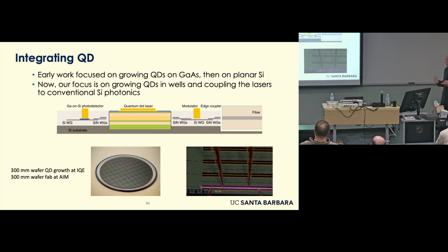So we've been growing these for a long time. Most of our work has been on planar growth. Most recently now, we etch these deep wells and grow all the quantum dots inside these wells. We have to do that to get the lasing region lined up with the waveguides in the silicon photonics. We're integrating this with SUNY's standard silicon photonics process, taking wafers that they have, all the modulators and detectors are already integrated on there. Again, it's 300 millimeter fab. We've transferred the growth to IQE, so if you want to buy quantum dot lasers, 300 millimeter wafers, they'll gladly sell them to you.